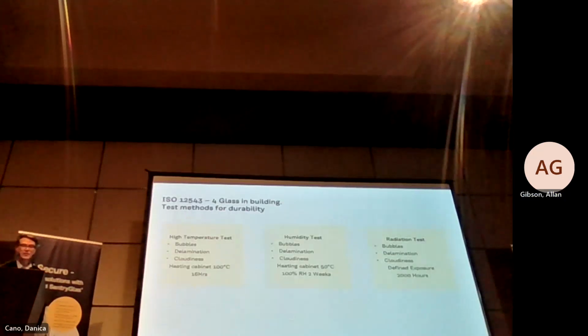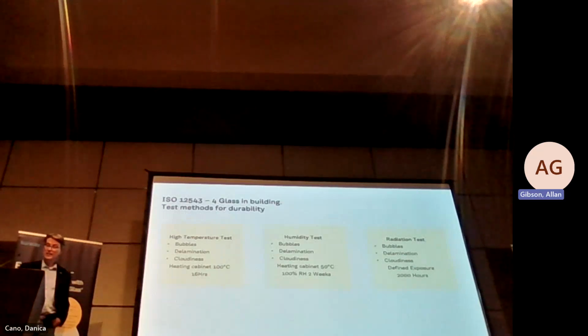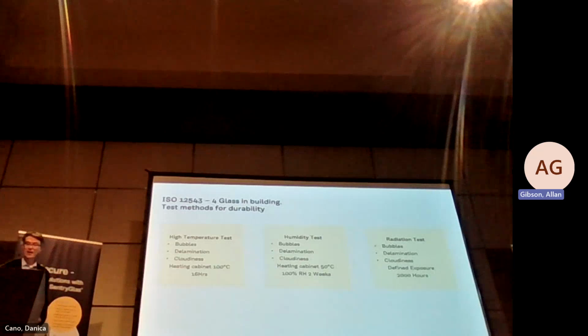Next slide, please. The test method for checking sealant compatibility is similar to the accelerated test that I showed you earlier to check the quality of laminated interlayer glass. But it also has some similarities to a performance monitoring testing regime that we have for SentryGlass samples. They're sent to our lab by a laminator to receive an approved SentryGlass laminator status, where the samples are subject to a bake test where temperatures are ramped up to 150 degrees, not the 100 degrees that you see there. Pummel test, lesion test, and we also test for moisture. But the sealants run through similar tests to those I showed you earlier.